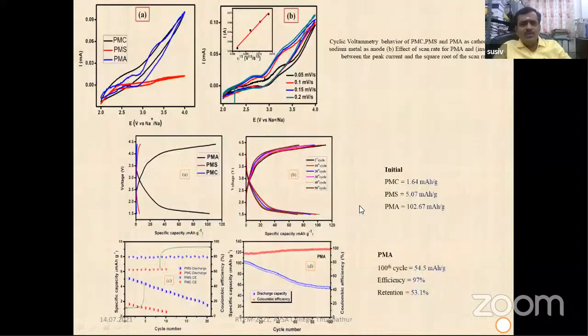See the charge discharge of this battery while using the chloride and sulfate precursor. It exhibits just 1.64 milliampere hour per gram and 5.07 milliampere hour per gram for chloride and sulfate. Whereas while using the acetate precursor, it gives 102.67 milliampere hour per gram, and it sustains up to 100 cycles with 54 milliampere hour per gram.